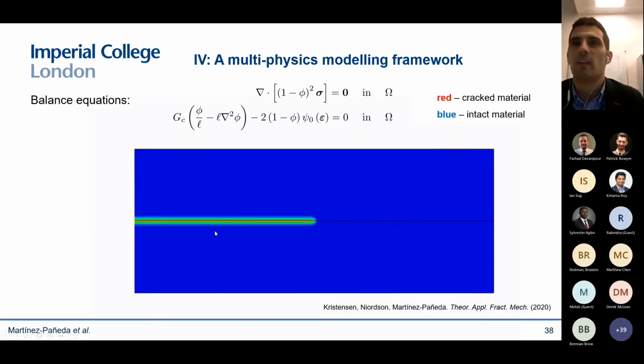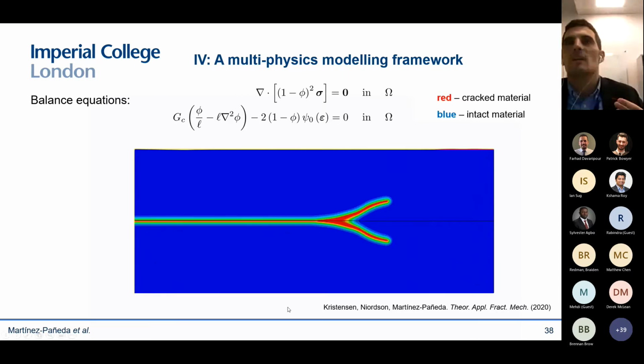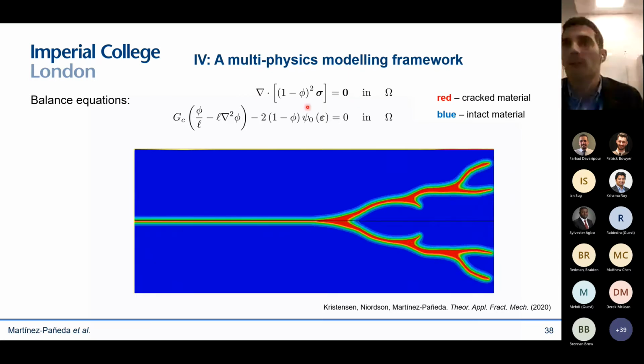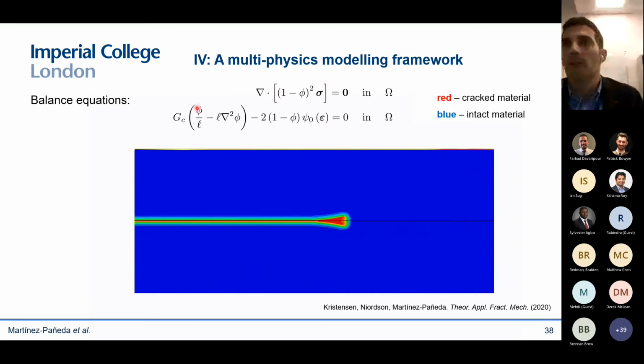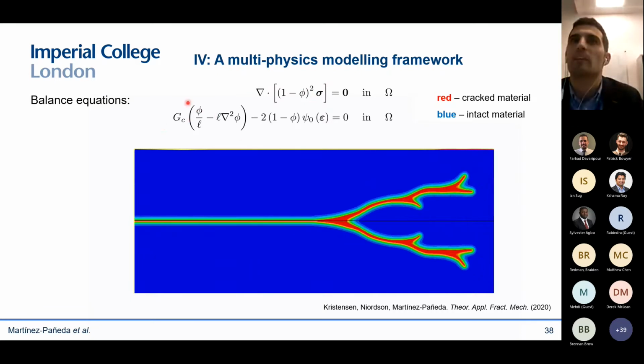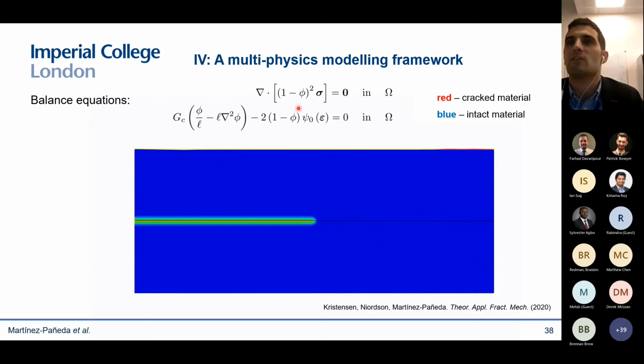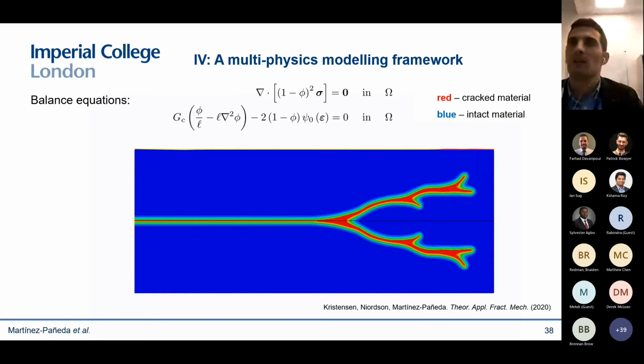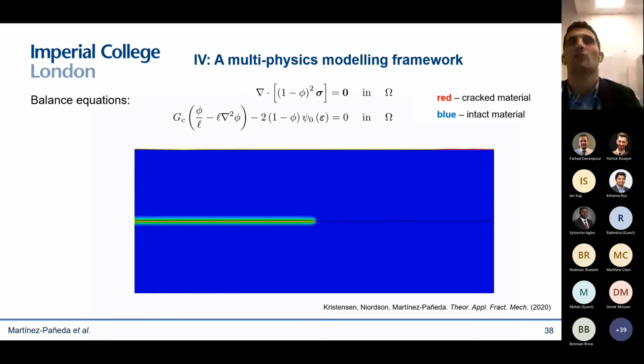But basically, at the end of the day, what you have is two equations, one for the balance of linear momentum, so the standard deformation problem, and then an evolution for the phase field, which is basically a competition between the fracture energy and the strain energy density of the solid that evolves with applied load. So it is the thermodynamics of fracture coming into play. So it is a method that is physically sound and at the same time is computationally very compelling.